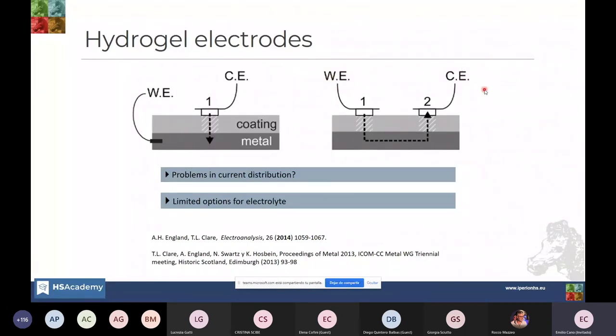We have some disadvantages. There might also be problems of current distribution, specifically when you have a low impedance coating, which is the typical case of many coatings used in cultural heritage. You can also have current flowing through the coating, as shown here by these arrows. So at the end, you don't know what you are really measuring. And finally, a very relevant problem is that you have limited options for choosing the electrolyte.